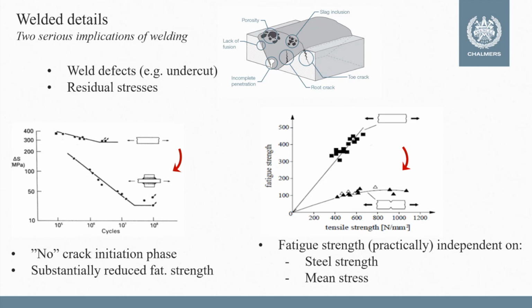This dependency becomes much weaker and more or less disappears when we introduce welds and weld defects in welded connections. And that is, of course, the reason that when we do fatigue design today for as-welded details, we don't consider the strength of the material as a parameter. So whether we have high strength steel or conventional construction steel, we don't care in the fatigue design. We don't take this into account because of this reason.